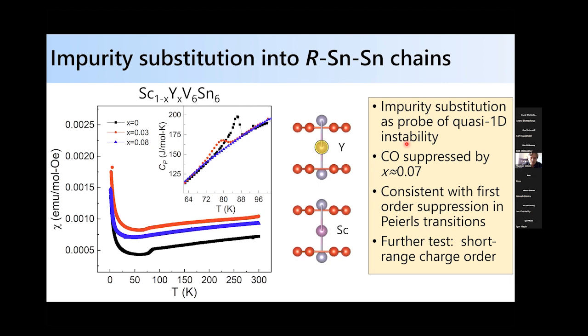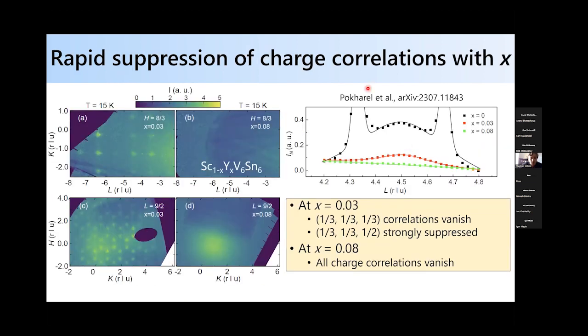And you can also examine it a bit more carefully and ask what the short-range correlations look like. What we find is that by the time you put 3% yttrium into it, you've completely disrupted the long-range order that we can see via X-ray scattering. Instead, you just have these remnant third a third by 2 type correlations in short-range order. And by the time you put 8% yttrium into it, basically all charge correlations vanish. So you have this really rapid suppression of this charge instability in this compound via just steric effects, or just a site substitution, isovalent substitution.